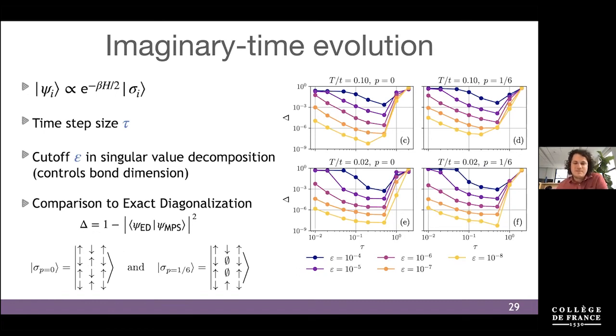So I'm taking the chance to present some results I personally really like, but maybe it's a bit for experts. Anyway, what we want to do is to compute this imaginary time evolution. And this TDVP algorithm has two main parameters. Similar to time integrators for differential equations, you have a time step size, the length of how much I step within one time step. The second parameter is the cutoff, which is related to doing singular value decompositions of the matrix product states in this algorithm.